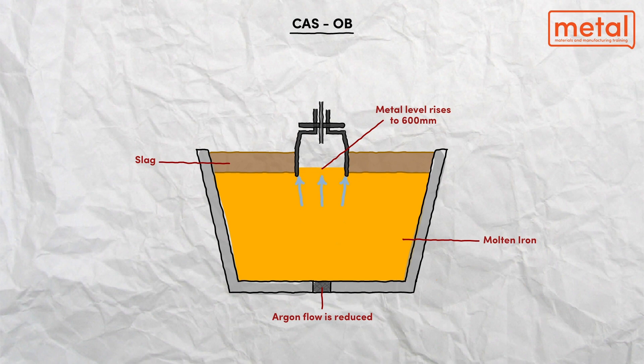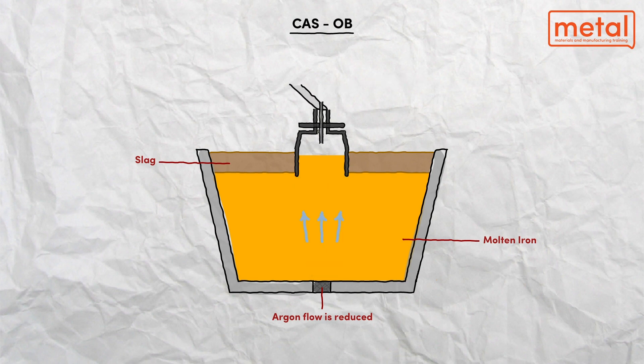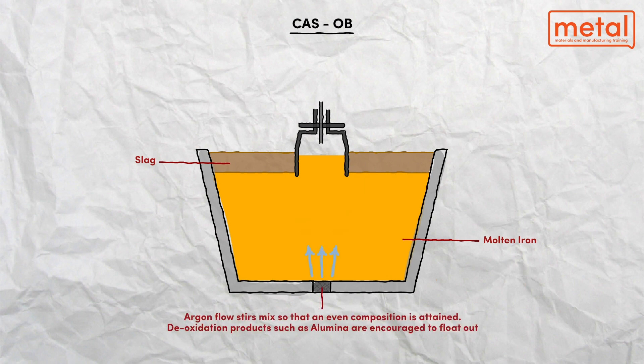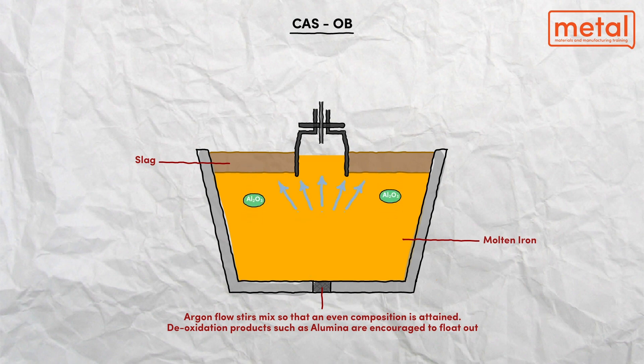The bell allows the simultaneous addition of aluminium and blowing of oxygen gas through a top lance. Due to the heat generated by the reaction of aluminium and oxygen, the liquid steel temperature can be raised by up to 10 degrees per minute. The aluminium oxide formed needs to float out to produce clean steel. Additional argon stirring if necessary is achieved through a specially shaped submerged lance, and further addition of ferro-alloys into the slag-free region achieves higher yield.